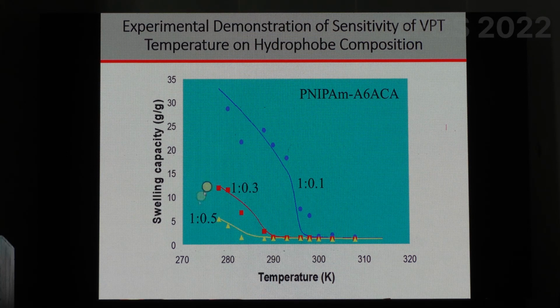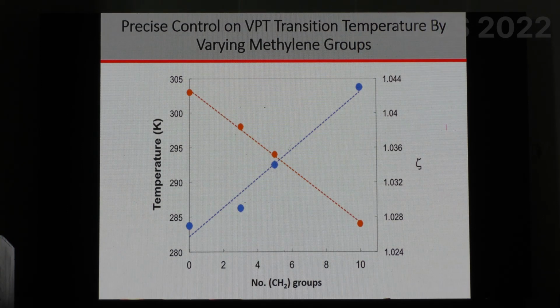So as I change the composition of this polymer, you can see that the phase transition happens at different temperatures, exactly as the theory predicts, and the lines are actually the theory. And the experiments and the theory also tell us how this small change in the hydrophobicity actually causes the change in the temperature at which the volume phase transition happens. And you can now link it to the chemistry: by changing the number of CH2 groups, I can actually control the temperature of phase transition and the subtle change in the hydrophobicity.